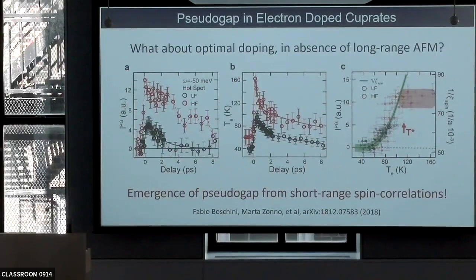So experimentally, there are issues with the sample aging and so on, but this way of approaching the problem is very fast and very accurate. So all of these fluences and delays can be turned into delay versus electronic temperature. Basically, at each delay, what Fabio can do is look along the nodal direction, look at the Fermi edge,